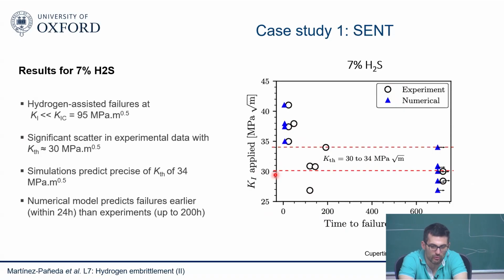The numerics are a bit more clean. They seem to be more or less in agreement, but the numerics are of course cleaner in the sense that we don't have the scatter intrinsic to an experiment. So we do get that if you go below 34 megapascals root meter, no failure happens. Well, in the experiment, we think the threshold is below 30 and 34, with some points even outside of that. So there's a bit of a scatter there.